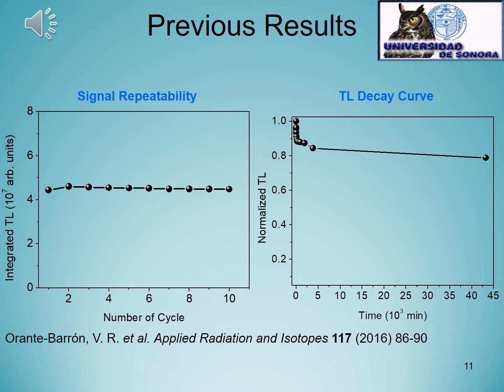Also, we can observe a very good signal repeatability, and as we can observe on the TL decay curve, we can see this asymptotic behavior during 1 month, which is very suitable for practical dosimetry.